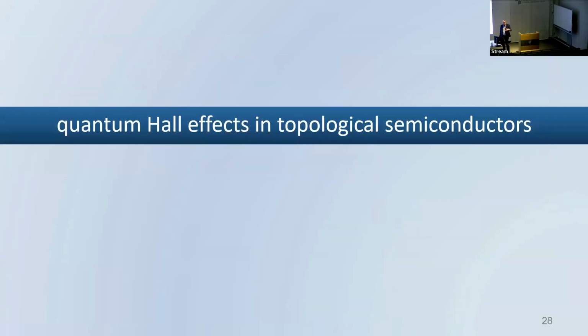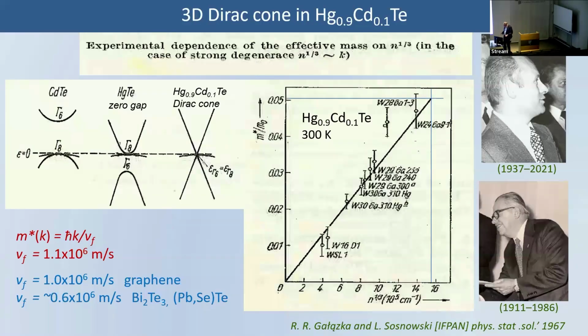Now we turn from the quantum Hall effect toward topological materials. Here you see an old paper showing what happens if you mix this inverted bandgap semiconductor with standard semiconductors. If you mix these two materials, at some point you end up in a situation where this gamma 6 band approaches the gamma 8 band, and k·p interaction means that you end up with Dirac cones. And this paper is probably the first observation of Dirac cones in a condensed matter situation.